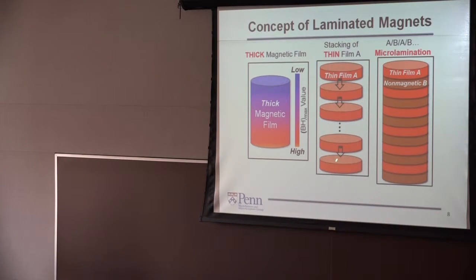But one problem with that is the alignment between the layers is hard. And sometimes in applications you want a precise location of your magnet, and that would be a problem. So the way that we utilize here is sequential multilayer electroplating. It's a self-registered process that is plated through the mold, where you have the thin film A, which is the magnetic material, and some kind of non-magnetic material, and you plate them in a lamination structure to have this AB microlaminated structure.